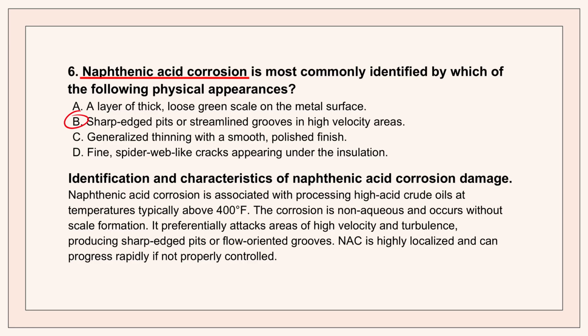Absolutely. That appearance, the sharp pits and the grooves, it confirms that fluid velocity and turbulence are central to the attack. So the acid attacks and the flow sweeps away any protection. Exactly. It sweeps away any weak protective layers that try to form. So NAC is always worst in areas of high turbulence: elbows, pump impellers, downstream of fittings.